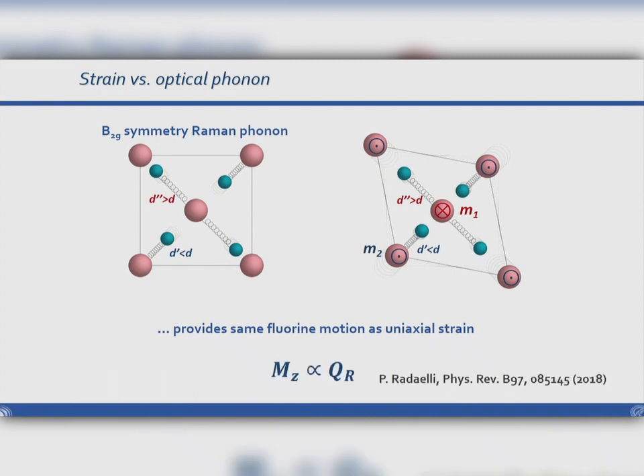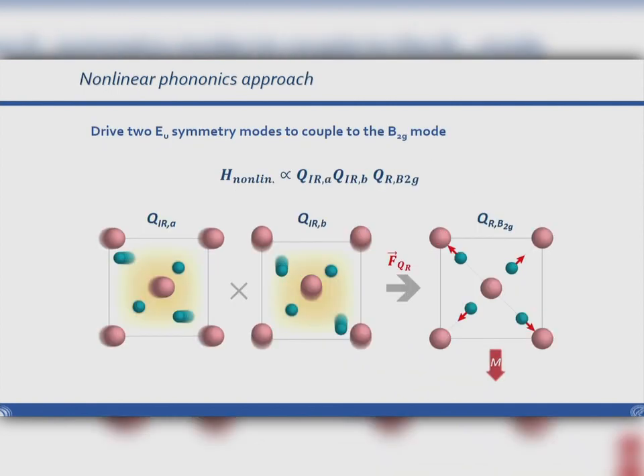And therefore, the idea was to find an excitation that can couple to this Raman mode. But as I said, it's a Raman mode, so light cannot directly couple to it. We need to couple to it via an IR-active mode. But because this is a mode that breaks symmetry, you cannot pump only one IR-active mode, because in a Q-squared fashion, this would only be able to couple to symmetric modes, so you have to excite two modes at the same time. These are two degenerate modes, one moving atoms along the a direction and one moving atoms along the b direction. But then the product will lead to the excitation of this Raman mode and will displace it in the same fashion as I introduced before for this Q-squared Q coupling in this general case.